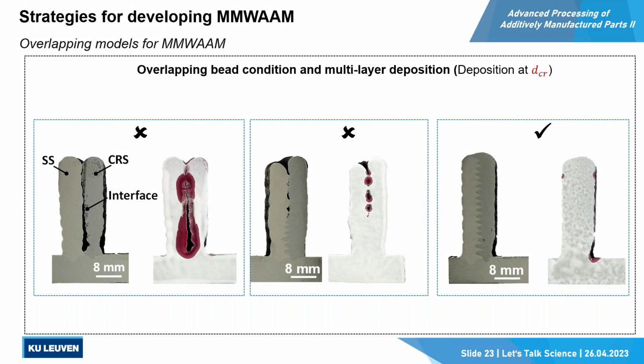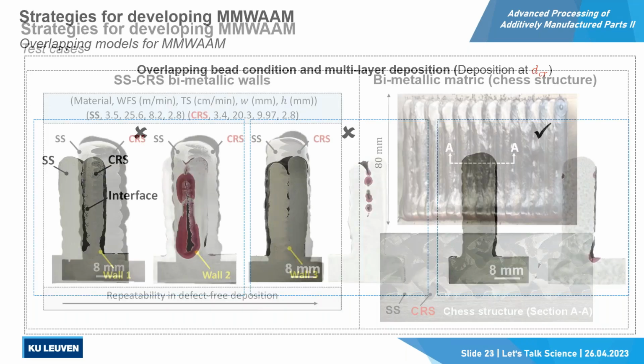You can see when it's two different materials, if you use the previous models, which are valid for a single material, in the middle and on the left there will be a lack of fusion in between the materials, and we cannot get an acceptable component. But on the right, using the new model, we are successful in having a defect-free wall. And in the last slide, I will show some test cases.